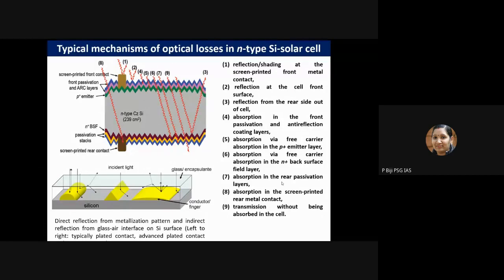So now if you see the metal fingers, the direct reflection from the metallization pattern can also influence such type of optical losses. This direct reflection from the metallization pattern and also the indirect reflection from the glass-air interface on the silicon surface. So if you see this particular figure, you can see that it has got different geometries. The first one from the left is typically a plated, electroplated contact. So that has got a different type of reflection losses.